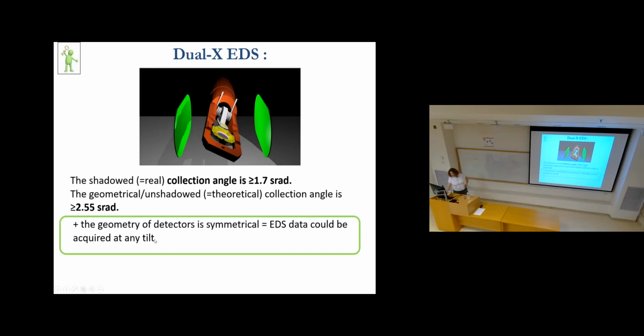So this means that from a very, very small and thin and tiny sample, we can acquire almost every emitted X-ray photon. So with our high brightness gun, we can scan with picoamps and with nanoamps. So we can generate a lot of X-rays. From the tiny region, we can collect almost every photon, and we can do that at any geometry, because unlike the previous configuration, when we had to tilt the sample towards the detector, now we can tilt as much as we need to orient the sample, but it will not affect the collection ability.